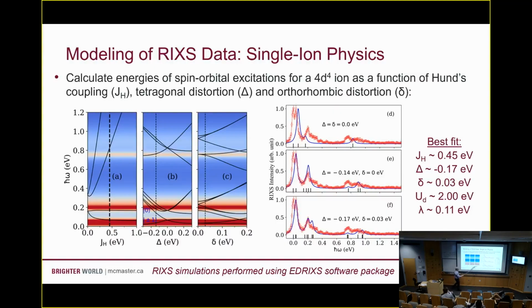Okay. And so you can see here that with Hund's alone and none of these distortions, we've got only 2 peaks. They're definitely off of where our expected peaks should be. We introduce the tetragonal crystal field distortion to get a little bit better. But you can see we're still missing some of the shoulders here on our higher features. We introduce the third distortion, this orthorhombic splitting, and we can get something that seems to match the data reasonably well.